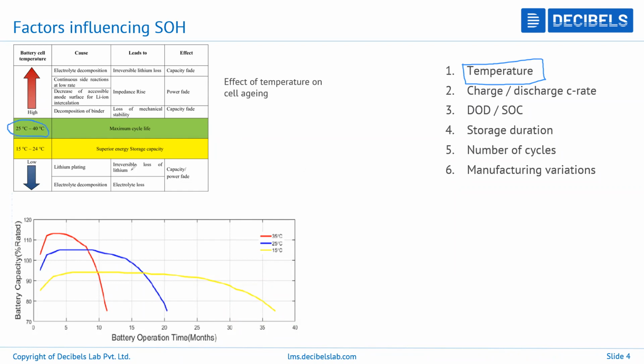The most recommended or nominal way in which you can operate the cell is between 25 to 40 degrees Celsius. Anywhere you go out of this, suppose you go to higher temperatures, say 55 or 60, you will see that the cell will start to degrade very rapidly. You can see certain things like irreversible lithium loss, rise in impedance, and then there is something called loss of lithium inventory. So you will no longer have the effectiveness of the electrochemical reactions occurring within the cell in order to give the required capacity.